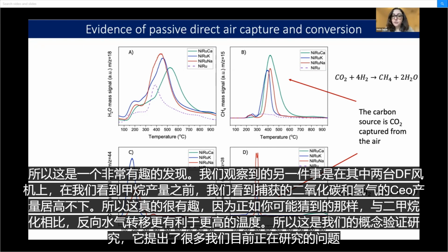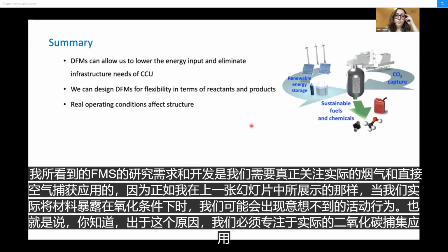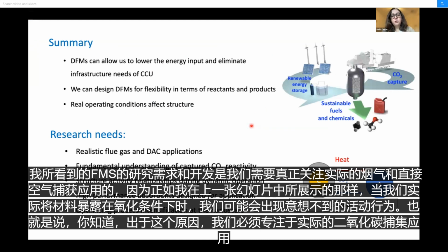So this was really interesting because, as you might be guessing, reverse water gas shift is favored at higher temperatures compared to methanation. So this was our proof of concept study, which opened up a lot of questions that we're investigating currently. And what I see as the research needs in the development of DFMs is, one, we need to really focus on realistic flue gas and direct air capture applications, because as I showed in my previous slide, we can get unexpected activity behavior when we actually expose the materials to oxidizing conditions. And we have to focus on realistic CO2 capture applications for that reason.